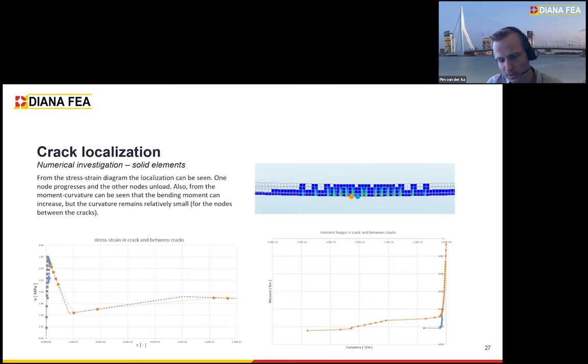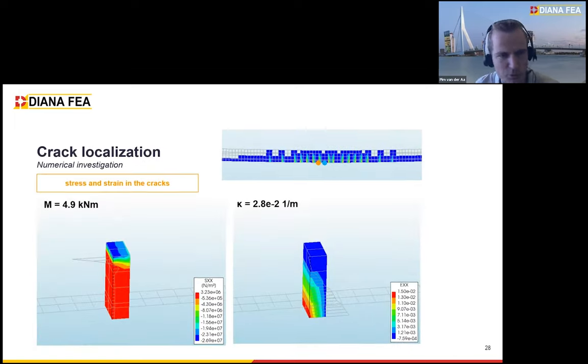To further explain the difference of the moment curvatures between the stress strain in the crack and between the cracks, I plotted the stress distribution over the cross section. You can see that on the left side. This is for an example when we are looking inside the crack. I hope it's a bit clear to see, but on the left side is the stress distribution, which you can see nicely follows the stress strain input we used for the model. And on the right side, you can see the strain, and you can see that it's actually still a linear distribution.